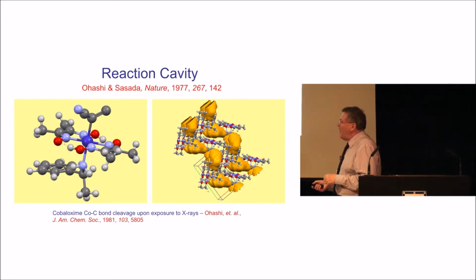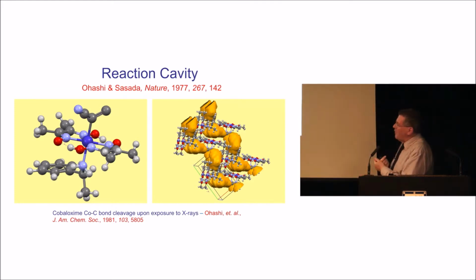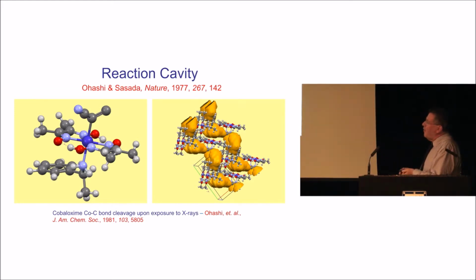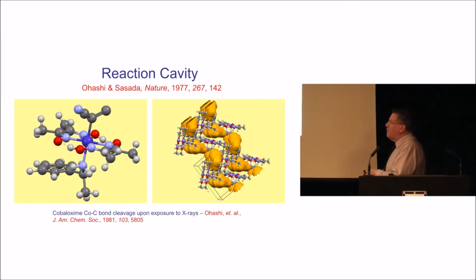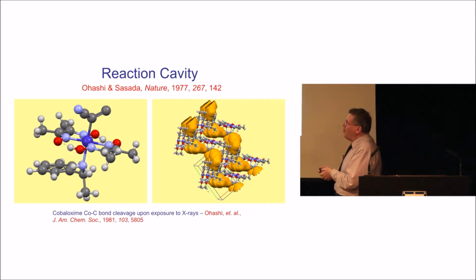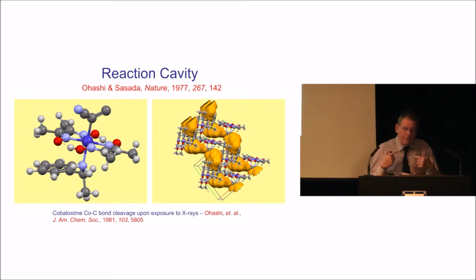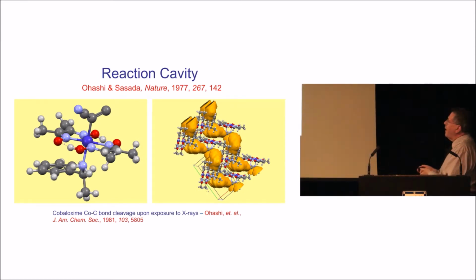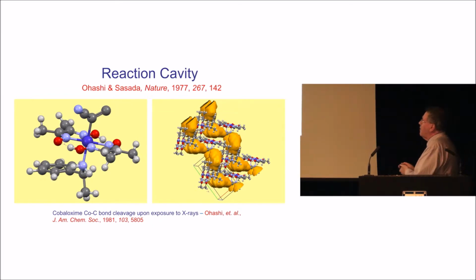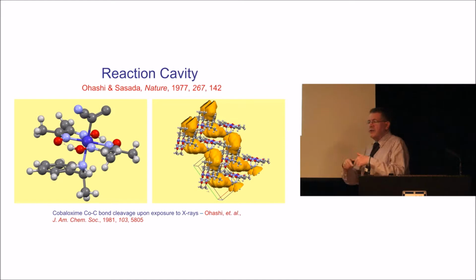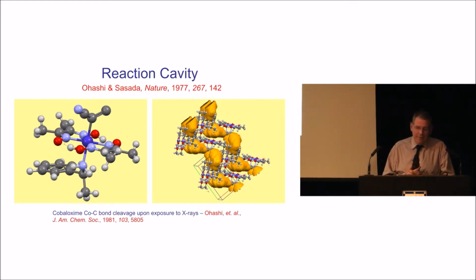Who looked at the first cobalt oxime complex, where in fact by X-ray damage there was actually a cleavage of this cobalt-carbon bond, and with that unit taken out you can see the cavity within the structure. So that's, if you like, the reaction cavity that allows that process to occur. So that's the sort of background to the work.